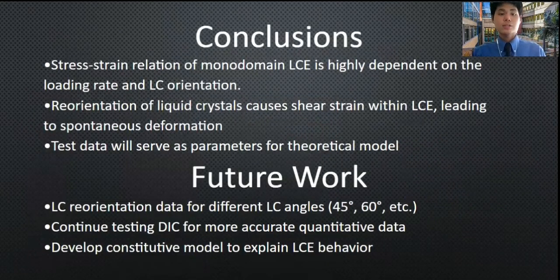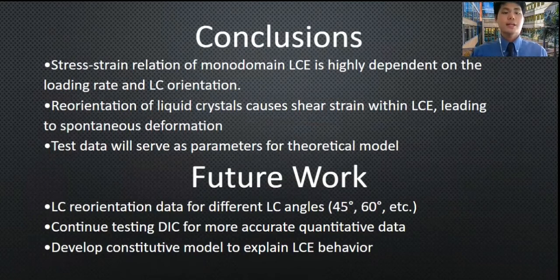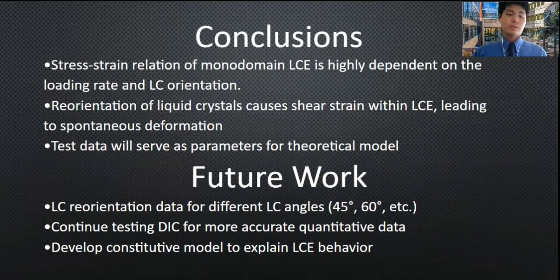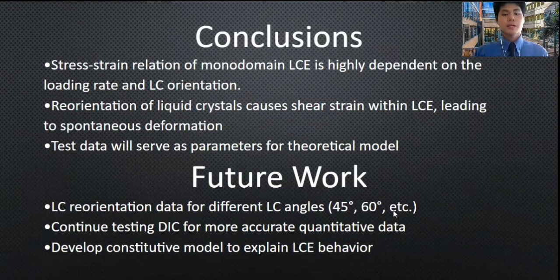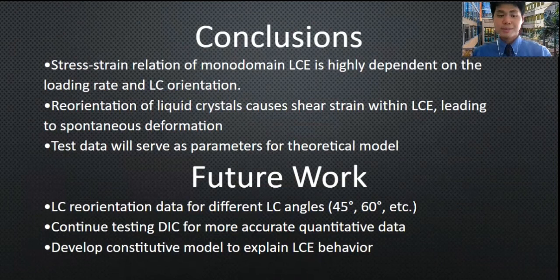In conclusion, we found that the stress-strain data we obtained is highly dependent on the loading rate and the liquid crystal orientation, and that when liquid crystals reorient they cause a shear strain within the LCE leading to spontaneous deformation. This is all experimental data that we hope will serve as parameters for a theoretical model in the future. We still have much more work to do: we only presented reorientation data for a 30-degree LCE, and we still need to test 45, 60, 75, and so on to confirm repeatability. We want to continue DIC testing to get more accurate quantitative data. And finally, the holy grail — we want to develop a constitutive model that explains all properties and behaviors of LCEs in one unified framework.